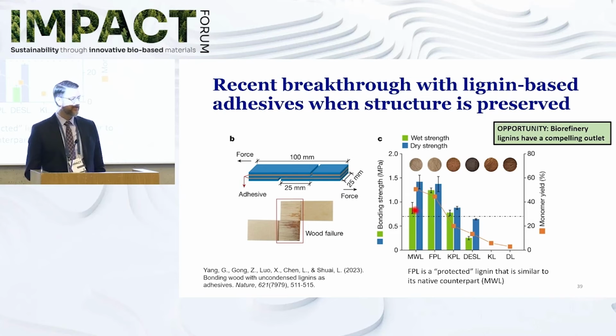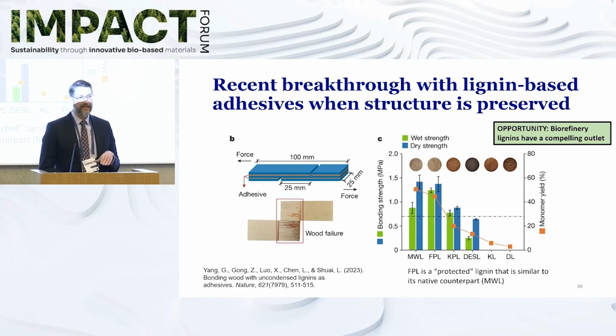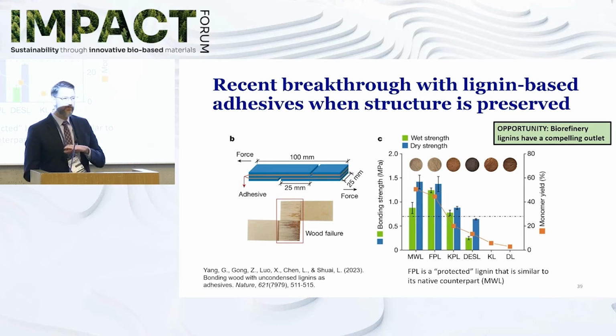And so this graphic over here just shows a variety of different lignins being tested, and the green and blue are the kind of the dry strength and the wet strength of the adhesives. And so I think there's a bright future in terms of using lignin for adhesives out there. We have some work in the past where we used laser modification to kind of erode the wood surface, and the remaining lignin could be used in a very similar fashion to the work that you see here.